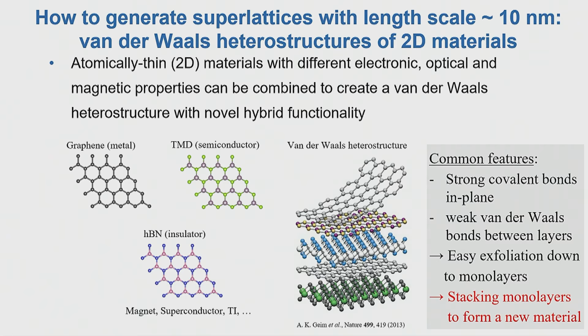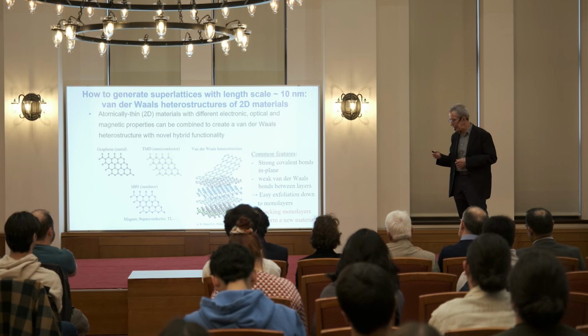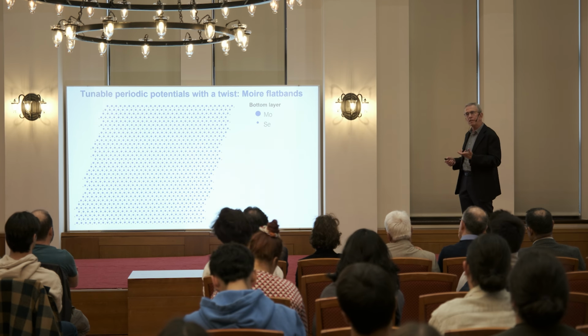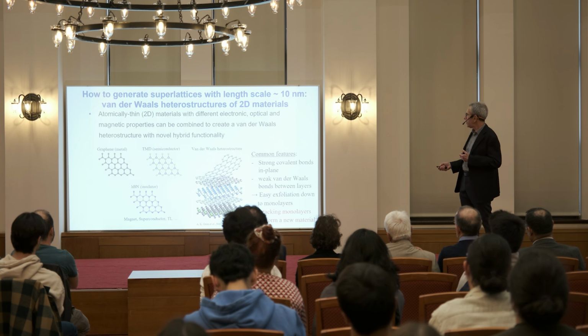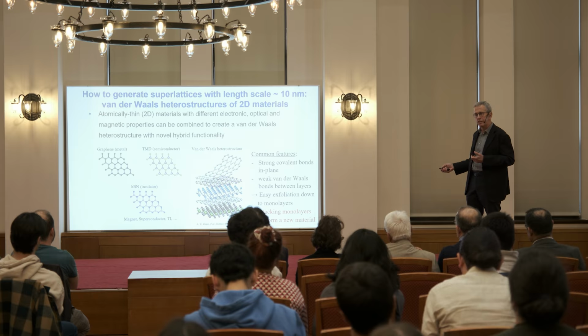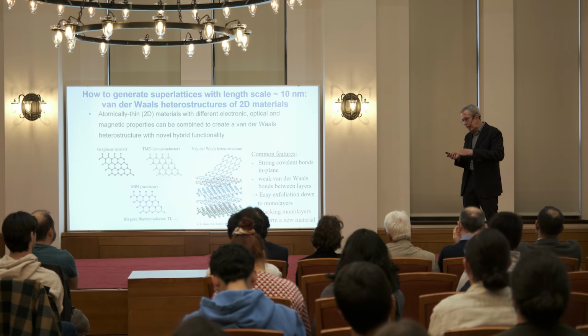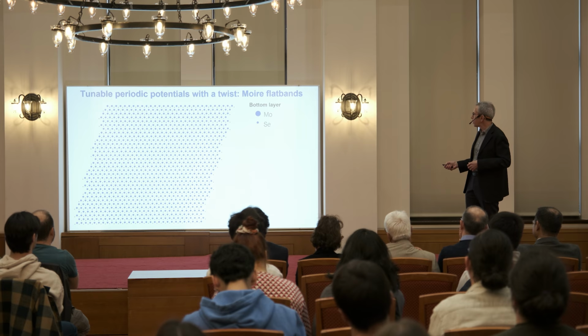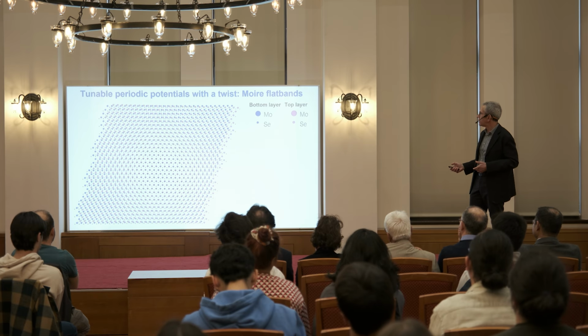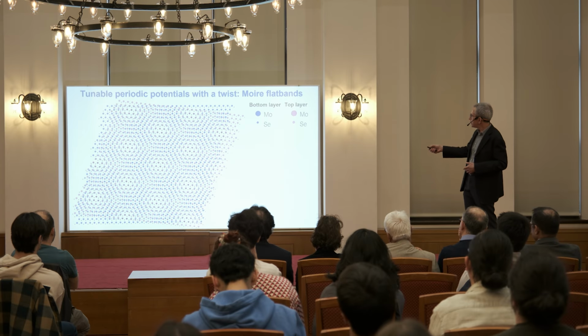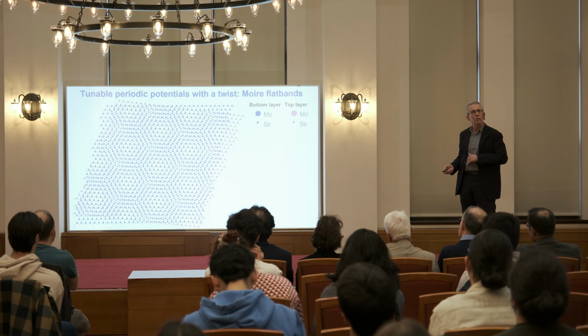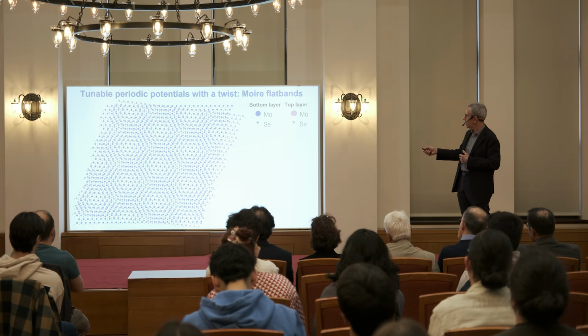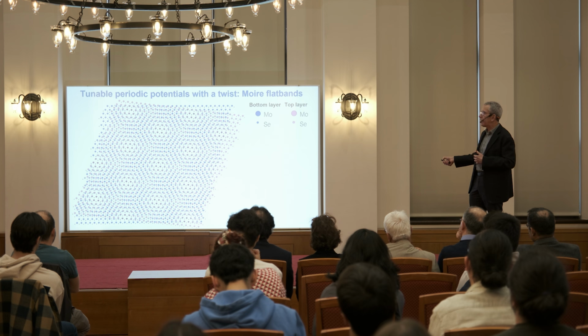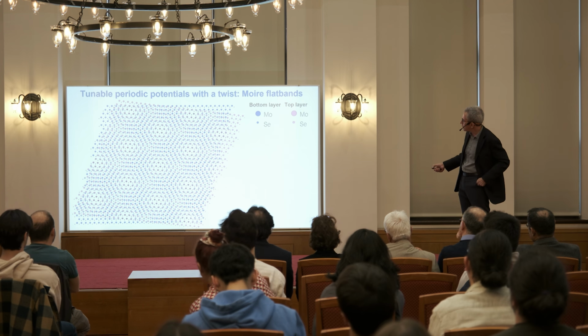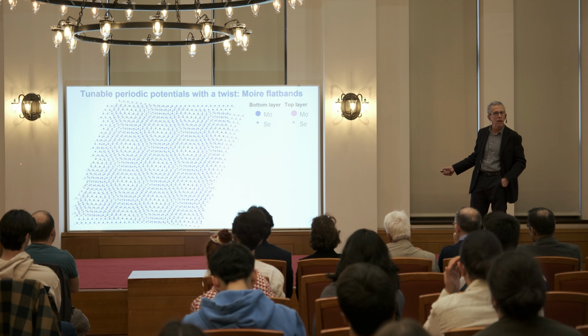Okay, so this was the excitement in the community, I should say, up until 2018, when it was realized that there is another degree of freedom that comes in this stacking process. That is, instead of trying to align these layers nicely and carefully, what you can do is misalign them while stacking. Okay? So in this case, this is a simulation of two molybdenum diselenide layers. These are semiconductor monolayers. And if you introduce a finite angle when you stack these two together, you see that there is a new superlattice emerging in the system.